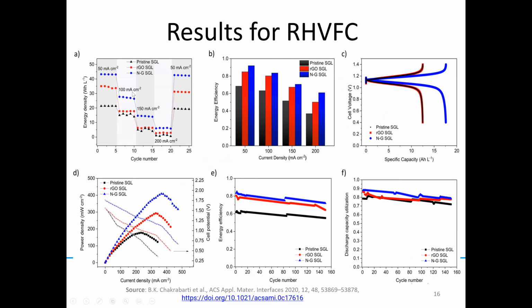Usually a commercial flow battery system operates between 80 to 120 milliamp per centimeter squared. So we are trying to see if we can go to higher current densities, and if we can do that, that means we can have lower costs by having fewer cells in a stack to give similar performance. So we try to go to as high current densities as possible to see how the modified electrodes would improve the performance of the hydrogen vanadium system.